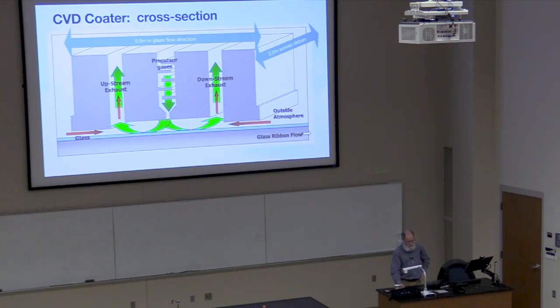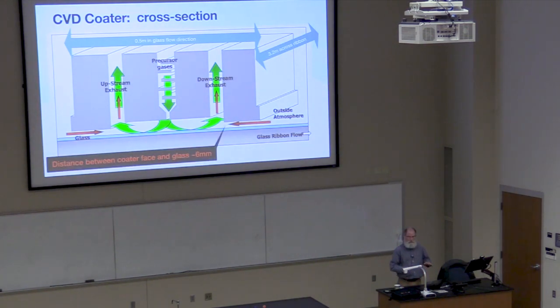So you can see we try to control it with gas flow and pressure, but it's still open to the atmosphere. The other thing about this coater is that the distance between the coater face and the glass is about 1/4 of an inch. So you've got a ribbon of glass that's 3 millimeters thick, you've got a coater that weighs several tons, and you're trying to lower it down so it's the same distance above the glass here as it is there, and it's not tilted either way. So that was quite an engineering challenge. I'm not an engineer, so that was quite a challenge to make that work.